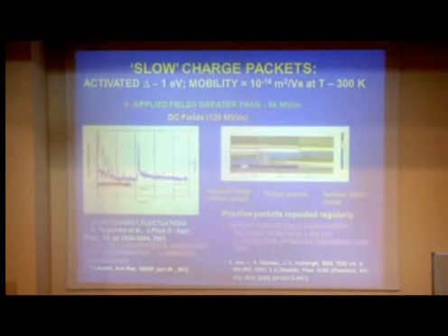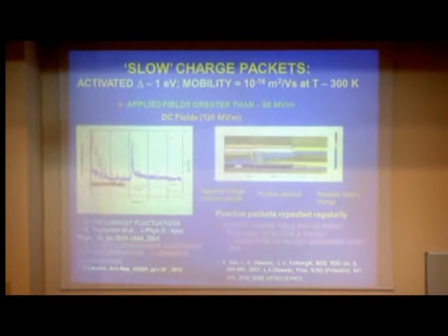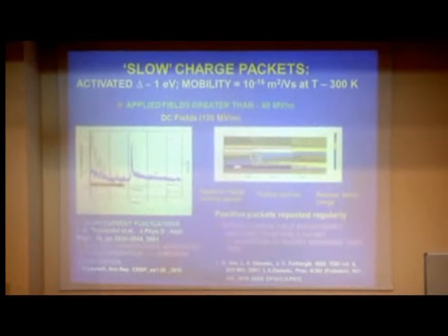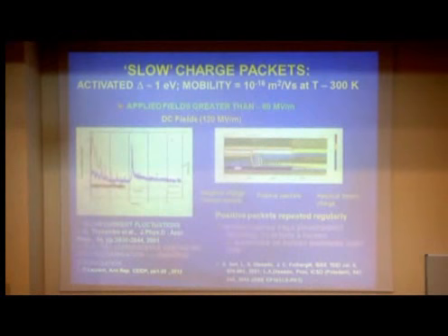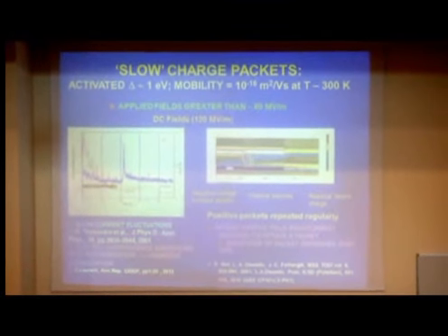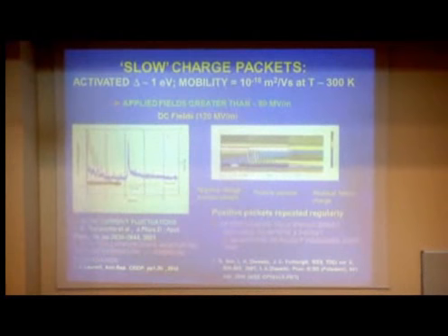That was the subject of the last Whitehead lecture. But we mustn't forget that the amount of charge in these packets is quite high. There is an electromechanical effect, compression and rarefaction, and this is repetitive. So we've got a fatiguing process going on at the same time as we might get chemical degradation. So there may be a route towards aging through such charge packets.